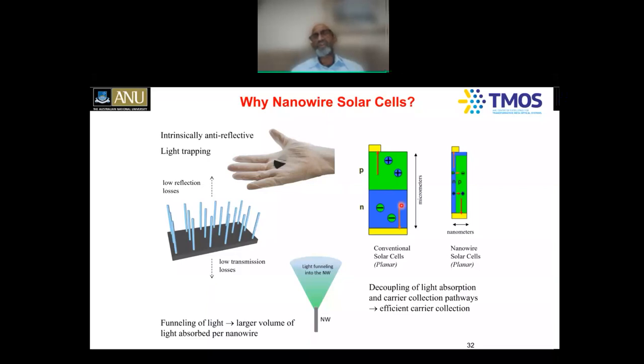And you say a solar cell is 20% efficient and 80% of the carriers have been lost, for example. But if you take a nanowire, you can make the nanowire as long as you want to absorb all the sunlight in the vertical direction. You can make a core shell p-n junction nanowire, so the carriers can be collected very efficiently. You're decoupling the light absorption pathways and carrier collection pathways, for example.